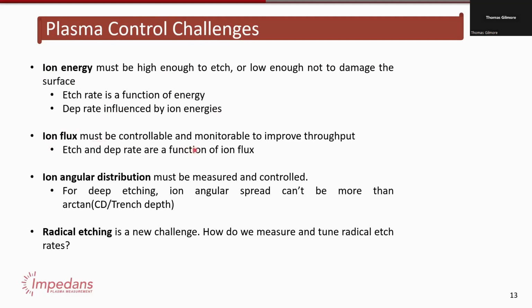The ion flux must be controllable and monitorable to improve throughput, okay? Because obviously etch and dep rate are a function of ion flux. So if you have a higher flux, you can do your process faster, you get higher throughput. But that also means you have to have very precise control. You don't want a really high ion flux, but your process has to be 1.2 seconds long exactly, right? That's not going to work.